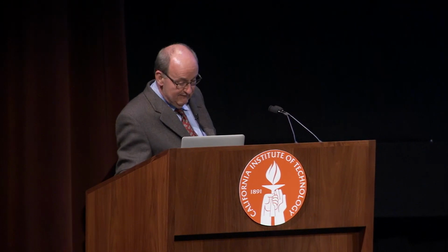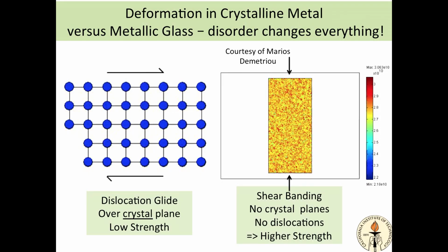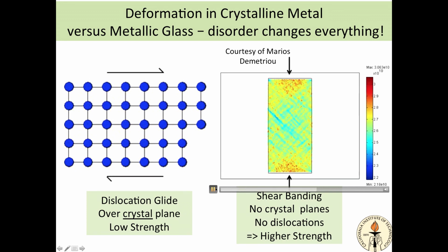Well, if you're in a crystal and you want to deform it, you try to shear it by pushing the top this way and the bottom that way. Crystals form dislocations, and this is how they deform. G.I. Taylor, 1934. That's the basis of modern metallurgy, dislocations. The stress that's required to make those dislocations move determines the strength of steel. Now, if I take a metallic glass, this is a simulation by Marios Demetriou, one of my postdocs who now works at our company. And if you do this on a simulation of an amorphous metal, it looks completely different. Eventually things localize into bands that look like the shear bands that we saw when we were bending it.